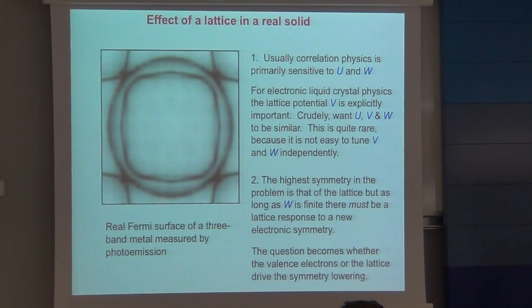The other thing which really complicates interpretation is that the highest symmetry, in the liquid crystal case, the highest symmetry you begin with are the full symmetries of the isotropic liquid. The highest symmetry you start with in a solid is the symmetry of the lattice, which is determined by this lattice potential. However, the electrons then make a Pomeranchuk distortion, say. They still have some finite coupling to the lattice, so if the outer electrons adopt a lower symmetry state, the lattice will respond to that.